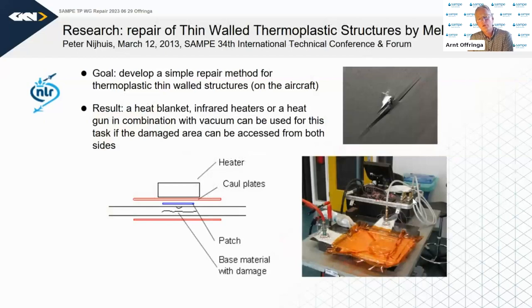In the Netherlands, the National Dutch Aerospace Center has done some repair research on unidirectional tape laminates with severe, local impact damages. And the research showed that with a proper heater and some caul plates, it is very well possible to basically remelt the material and to fuse together the fibers to a large degree. However, the challenge is to support the thermoplastic laminate while it is in the molten state.